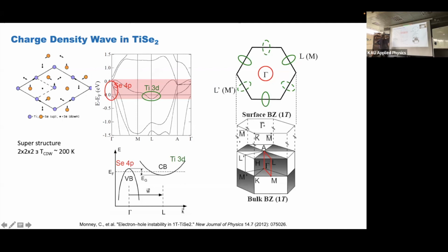It's like 0.05 angstrom. So you will not see it by eye if you take the structure in VESTA. You should only calculate it. In VESTA, the lattice parameter will be like 3.5 or so angstrom, so you will not notice it by eye. But this displacement exists in nature, and it creates this CDW structure, this 2x2 huge CDW structure.